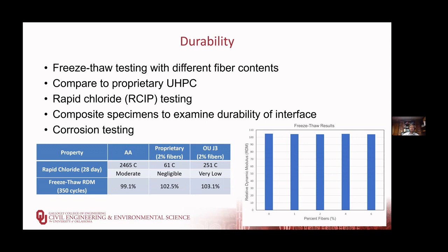And then we also wanted to look at what would happen if we had a composite specimen that was conventional concrete connected to UHPC, which is what we're often going to have in the field. How does that interface stand up to freezing and thawing over time? We also looked at some corrosion testing, which I won't discuss here today.